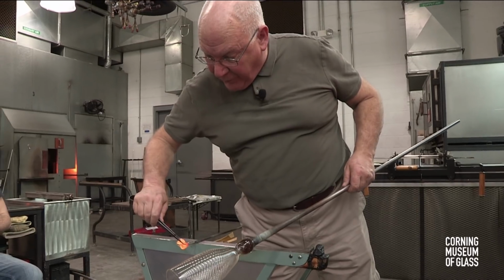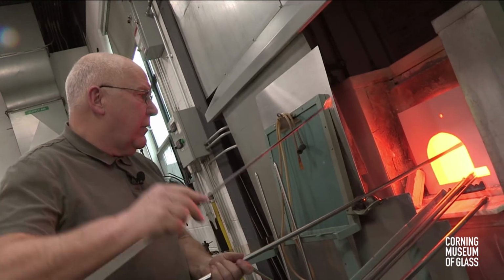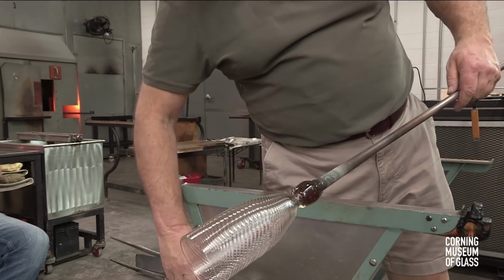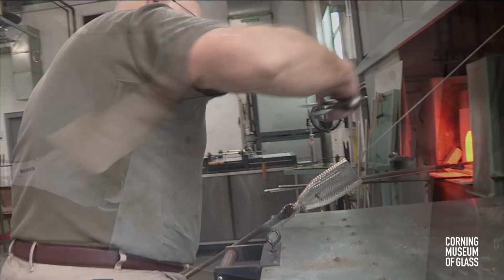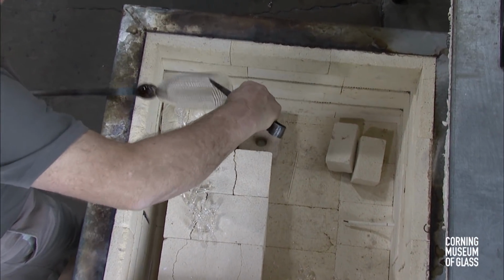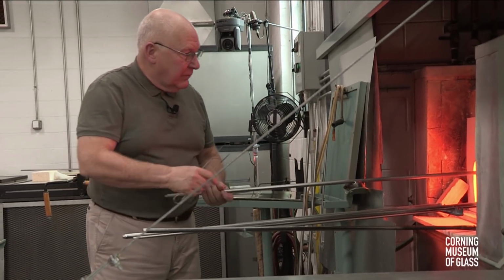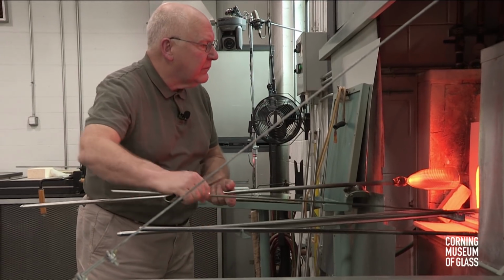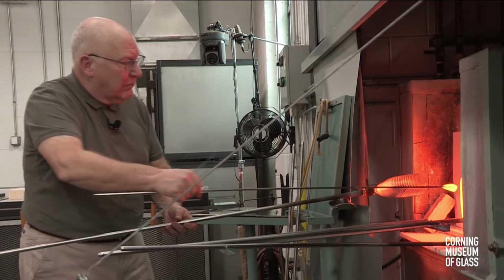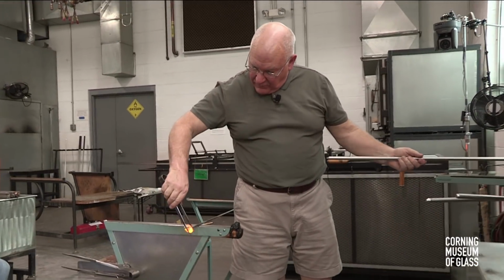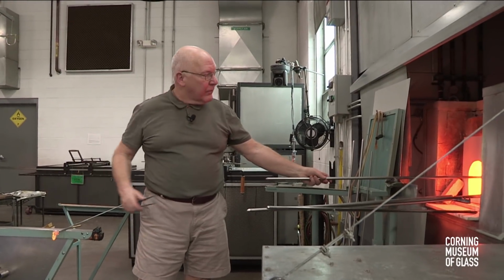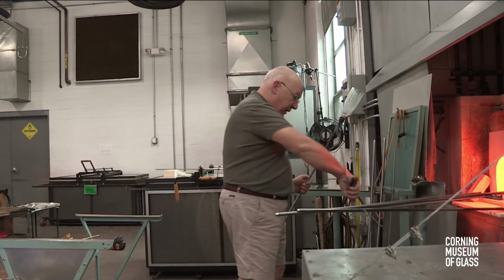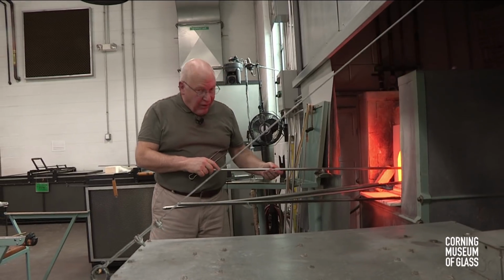I'm going to heat the pincers so I don't crack the cup when I grab it, because my next thing is to put it in the pickup box. Going to chill the neck and put it in the little holder. I actually cracked the rim when I grabbed it. The pincers weren't hot enough, but the crack healed.